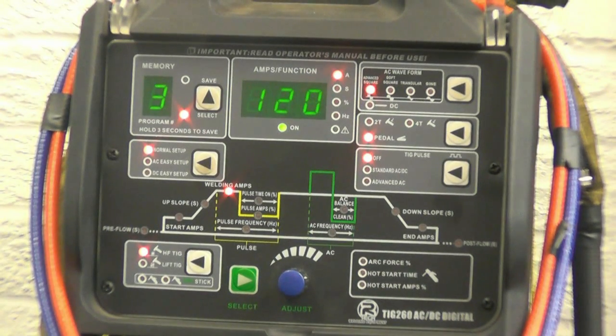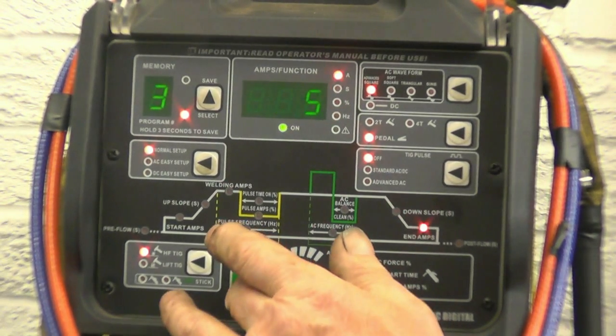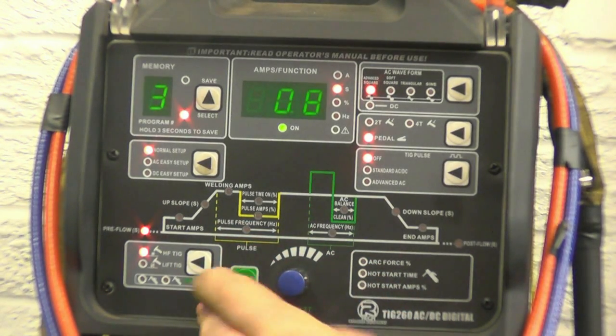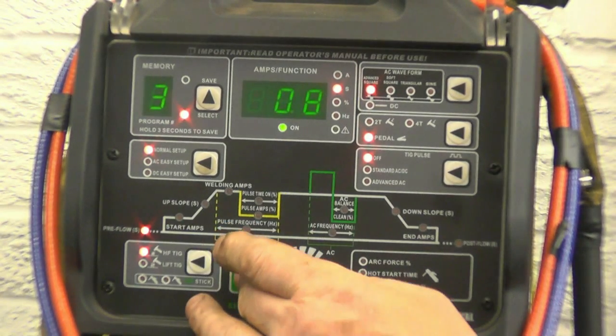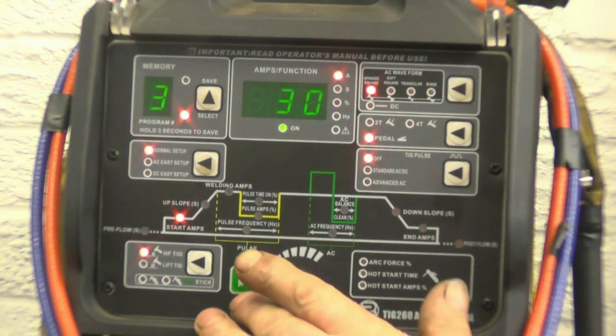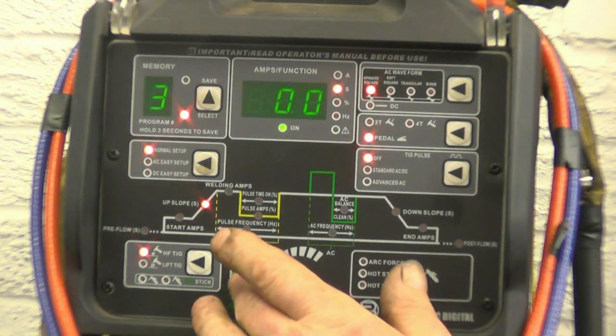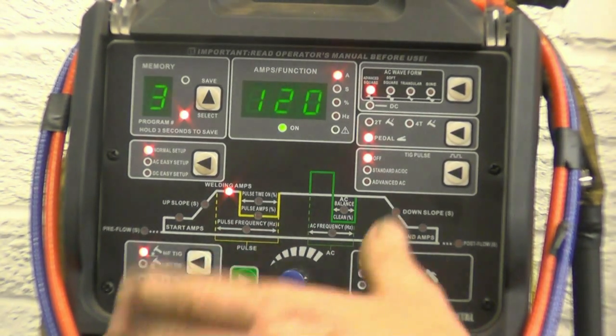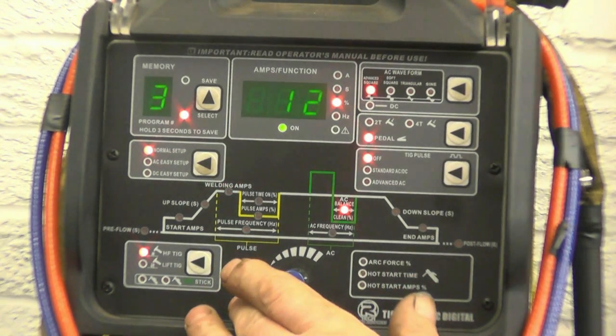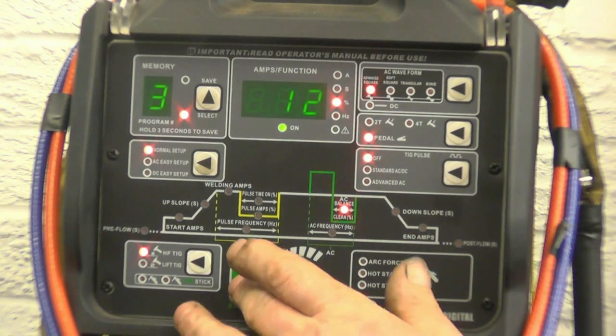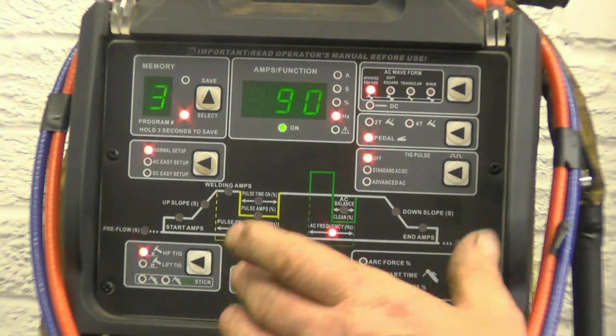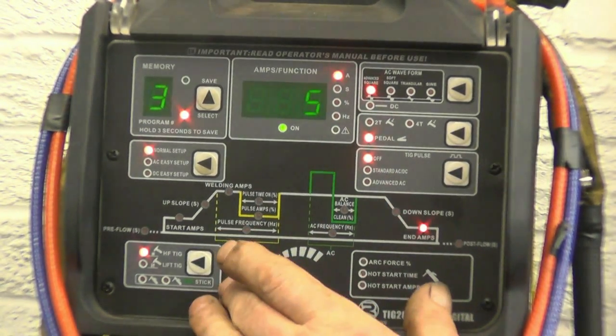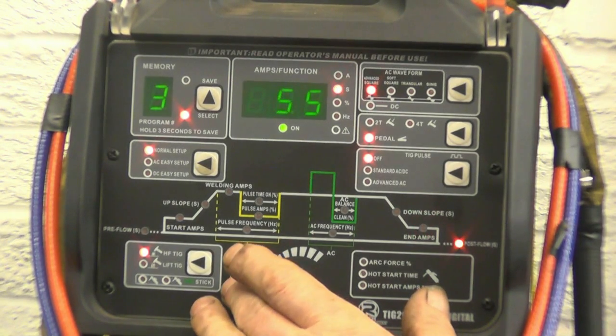Right, I'll go through the settings that I use to weld it or to braze on this AC/DC TIG welder. I use setting 3 on my welder. We'll start off at the beginning. Pre-flow gas. I don't use any pre-flow because I'm using a pedal. Start amps 30 amps, so I get a nice clean start. No upslope. Weld amps I've got set at 120, I use nowhere near that. Go on to AC balance, I've got that set at 12% and the frequency is at 90, so I'm welding this on AC. Downslope I don't use. End amps as low as it'll go.